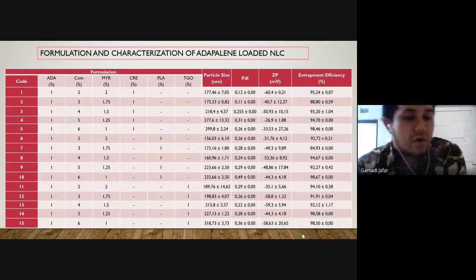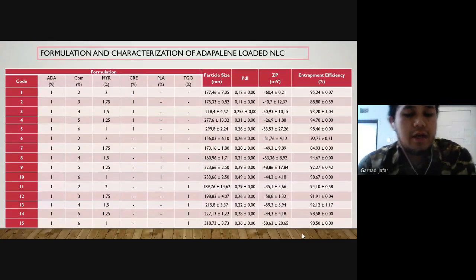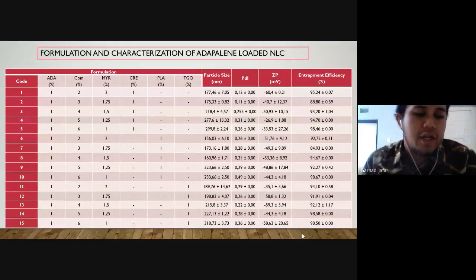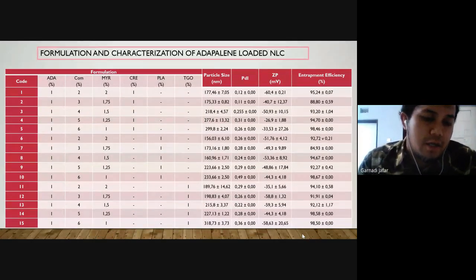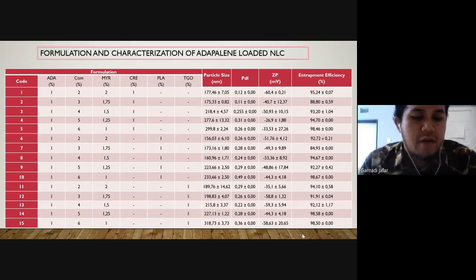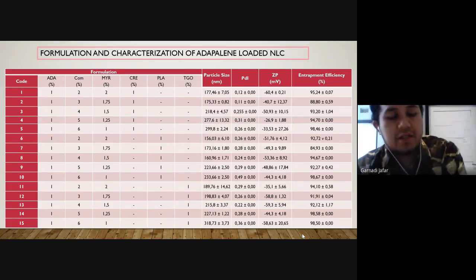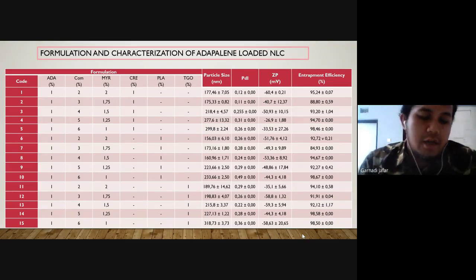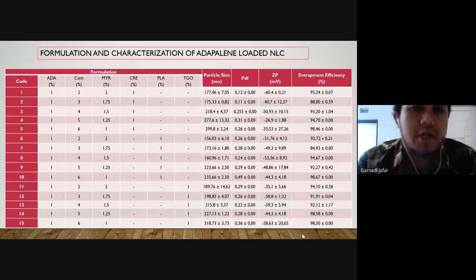From the results of the characterization, the particle size of adapalene NLC is in the range of 100 to 500 nanometers. This has been shown by many research journals about NLC for topical administration routes. The polydispersity index is below 0.5. This indicates a good particle size distribution in NLC adapalene. And the zeta potential value is in the range of minus 30 to minus 60 mV, which indicates a good level of stability in adapalene NLC. And then the last characterization, the entrapment efficiency, shows quite a good result, which is above 85%. This shows that Compritol can properly encapsulate adapalene.